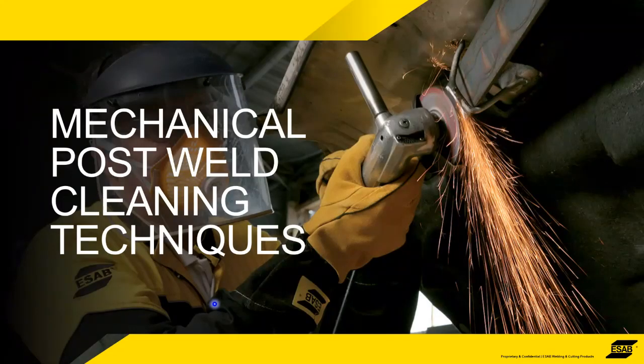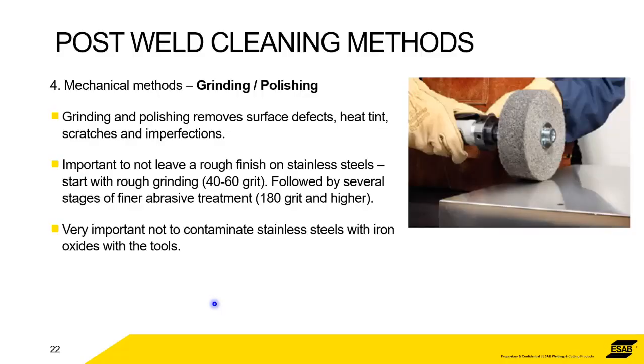Mechanical post-weld cleaning, not surprisingly, we see grinding and polishing, and the way to attack it really is to start off removing what you need to, basically, but then polish it up so that you don't leave a rough finish. The smoother the finish that you can leave, the better it will be. It gives more of a chance of the stainless forming this passive chromium oxide layer, and it looks better. The appearance is obviously a lot better.